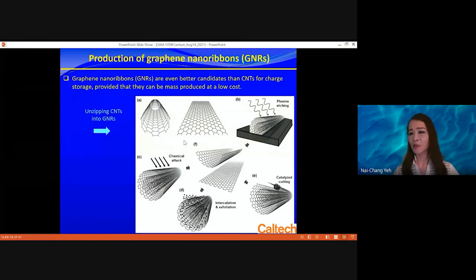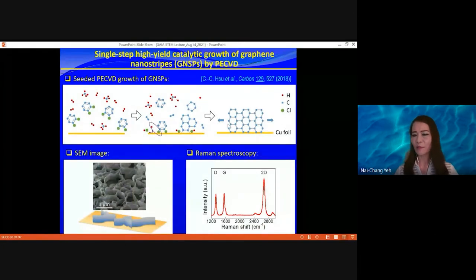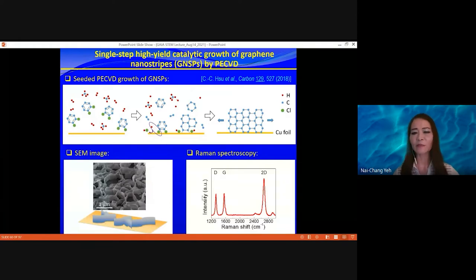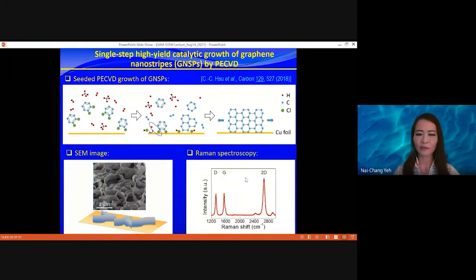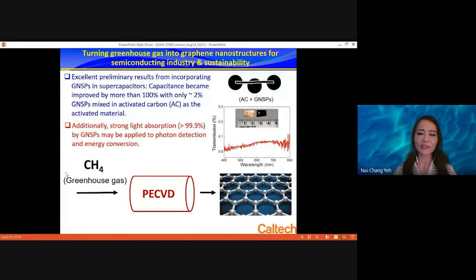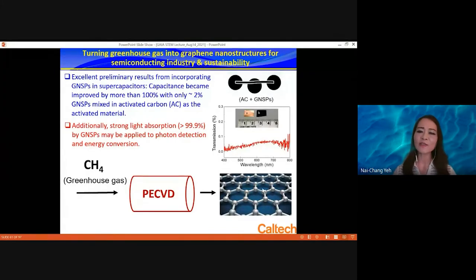This unzipping process is costly — you have to make carbon nanotubes and then unzip them. We have been able to develop and grow quasi one-dimensional carbon materials directly. Spectroscopy shows they are very high quality material, and we can use them for very good capacitor performance. You can take greenhouse gas and run it through plasma-enhanced chemical vapor deposition techniques to make nice graphene for all kinds of devices or energy storage.